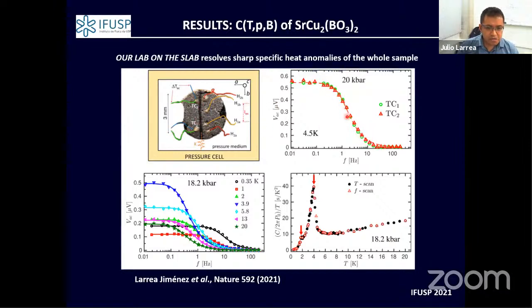This tells us that we don't have a temperature gradient across the sample, and in addition, that the specific heat we are measuring is taken from the whole sample.